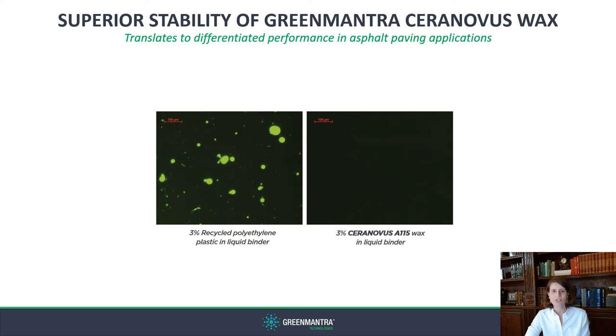The first image shows FM analysis of 3% unmodified recycled polyethylene plastic in a standard asphalt binder, demonstrating a high level of undispersed agglomerated plastic particles. In contrast, on the right, you can see 3% Green Mantra wax in the same binder. The total absence of the light green particles is indicative of a completely homogeneous mixture.